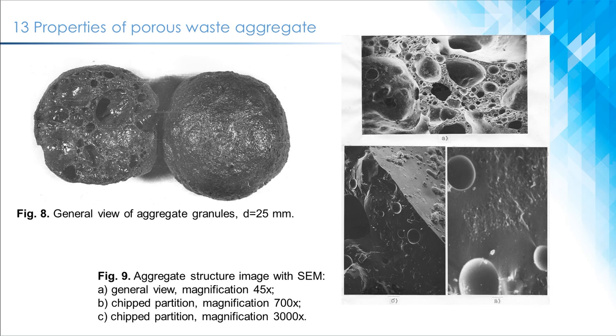The general view of the porous aggregate granules from the MBC wastes is shown in figure 8. The samples of the obtained porous aggregates, of dark brown color, differ little from each other and have a large porous structure with cavities. The pores are generally round, 250-1000 microns in size. The surface of the aggregate is partially melted and differs from the inner layers in its lower porosity. The absence of a dense sintered crust on the new aggregate's surface is expected to increase adhesion to the cement stone, ultimately leading to an increase in concrete strength.